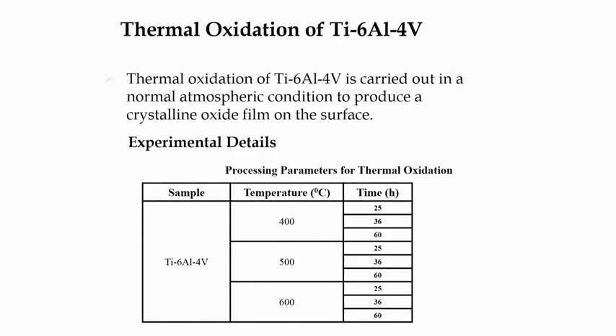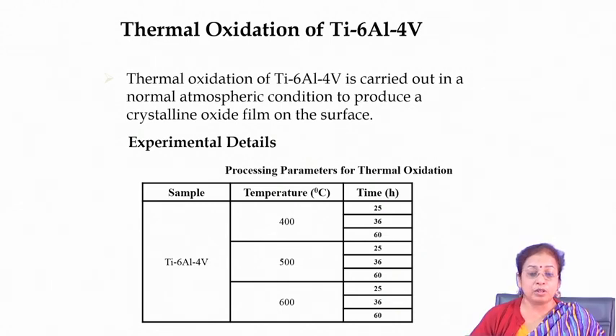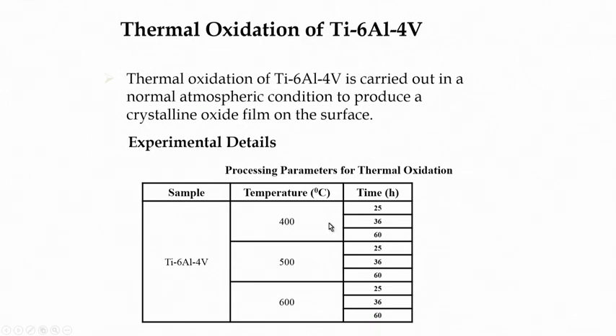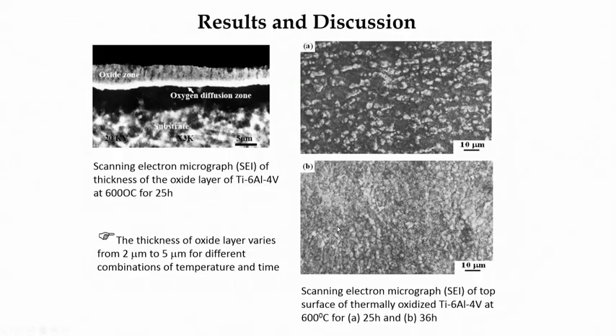So, in order to have full coverage of the surface, we tried to go for the thermal oxidation process. Thermal oxidation is another route for oxidation of any metallic materials, maybe iron and its alloys, steel, or titanium 6 aluminum 4 vanadium, or magnesium 2. Any metallic material can form oxide when you heat it at a higher temperature in an oxygen containing environment, or maybe in air. In this case the thermal oxidation treatment was carried out in air, and temperature was varied from 400 to 600 degrees Celsius, and time was also varied, and we tried to optimize the time and temperature combinations to have the desired microstructure and properties on the surface.